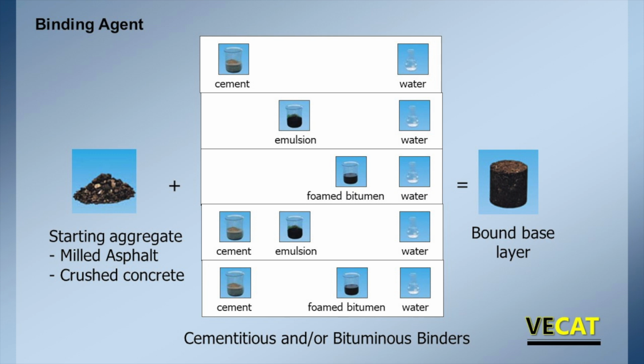So common binders, we're going to start with whatever our base material is, millings or crushed concrete. Most popular today is cement because it's low cost, $100 or $120 a ton, wherever you are around the country. But more is not better when you're putting cement in. Emulsion is popular in thinner lifts where you can get the water out quickly. Foamed asphalt or foamed bitumen is probably the most popular binder across North America today in these plant mixes. And then a combination of cement and emulsion, and cement and foamed asphalt.